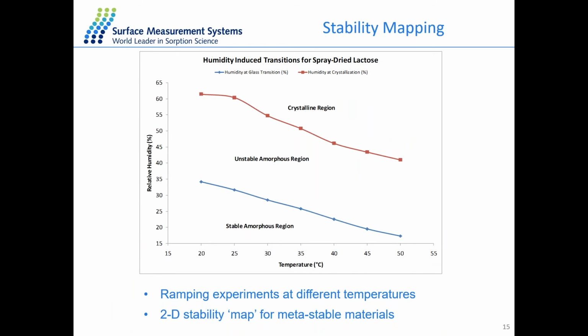And if we do a series of ramping experiments at different temperatures, we can then get this kind of stability mapping between the temperature and relative humidity. So here the blue line is for the glass transition for the sample, and the red line is the crystallization of the sample. And from this stability mapping, we can easily predict, at a combination of the temperature and humidity, whether the sample is at a very stable amorphous state, or the crystalline state, or just unstable and may change the structure anytime during the experiment or the performance.